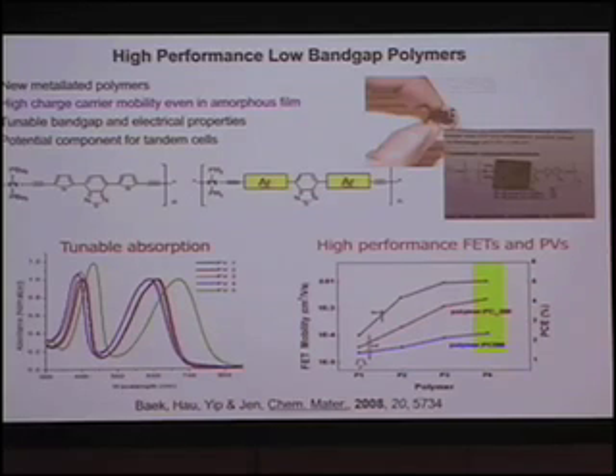How about new device material composition? Okay, it can allow you to really harvest the whole sunlight spectrum and also improve your device efficiency. You can see this is a metalated polymer. It's relatively transparent, okay, but then it has a relatively high mobility, 10 to the minus 2, very high mobility for this kind of amorphous material compared to the crystalline material. Okay, you already have very high mobility, but still relatively transparent. So this kind of material will be an ideal candidate for laminate between window type applications.